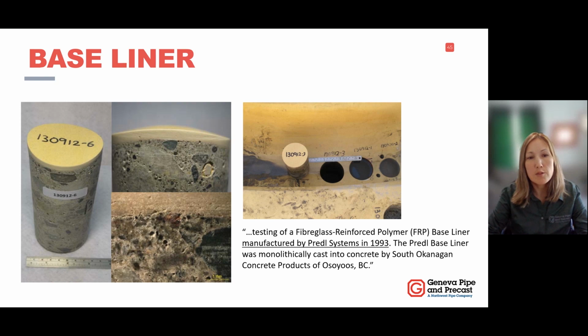And after some time, 20 years, 35 years, they will go back and they do find corrosion behind the liner. The most likely reason is because the welding has not been done through properly, and you probably had some defects in the welding where your environment could still penetrate through the liner and behind into concrete and create corrosion. But anyway, if you're looking at this cutout, they dug out one of the bases and they cored it, and they wanted to look at the thickness before and after, and they did not see any deterioration in the liner, and they did not see any corrosion behind the liner. So this is a great indication that this liner works, and it can seal and protect concrete for years.